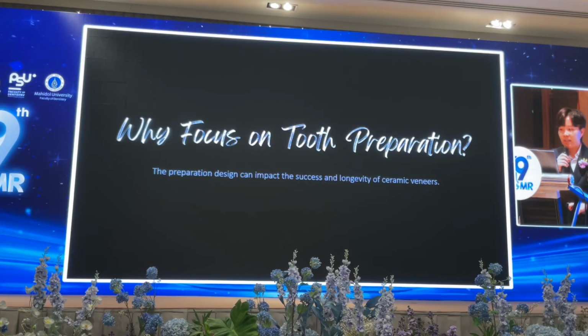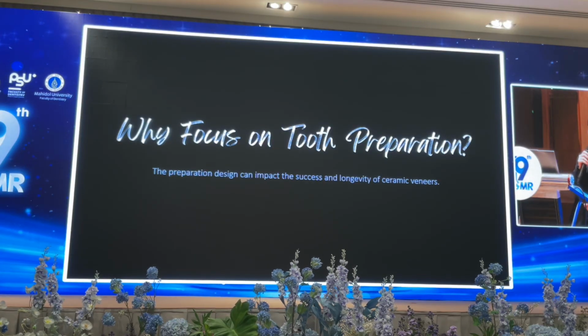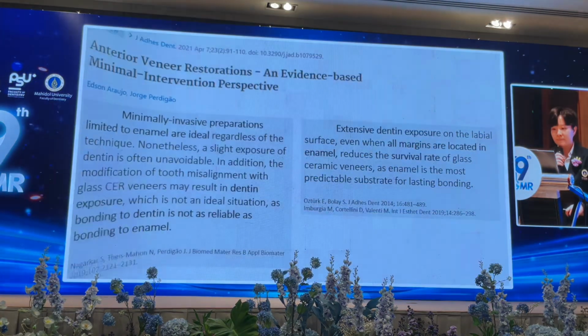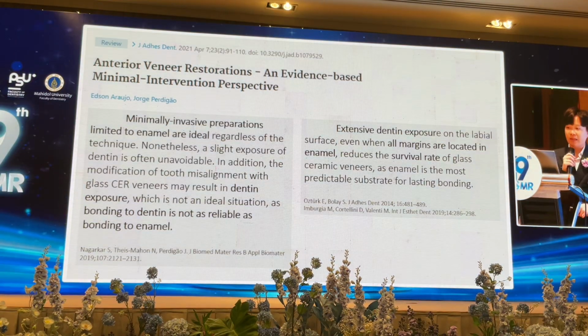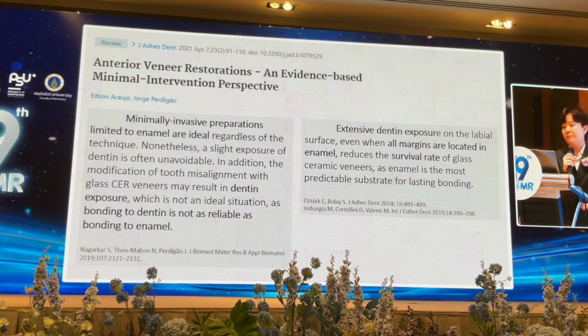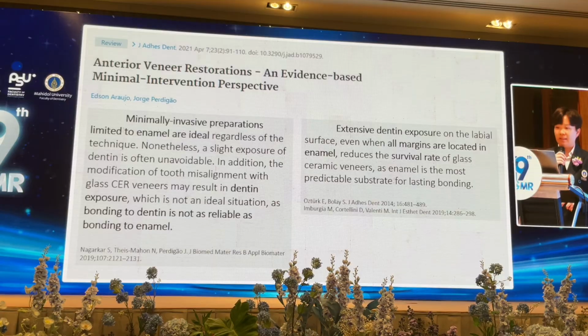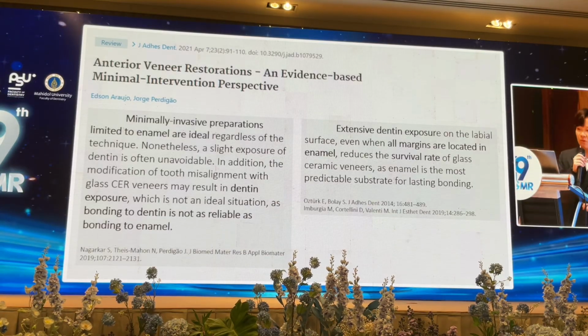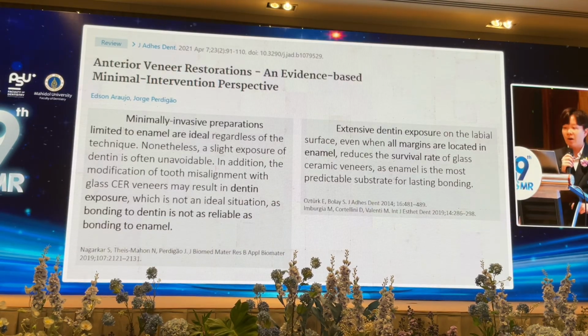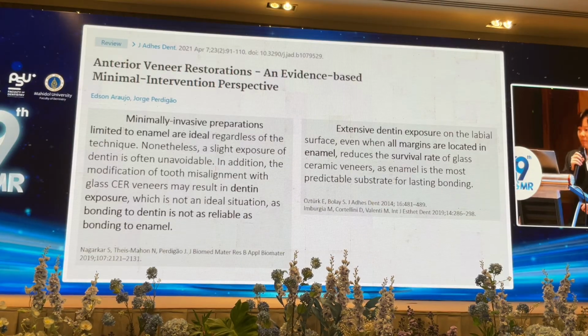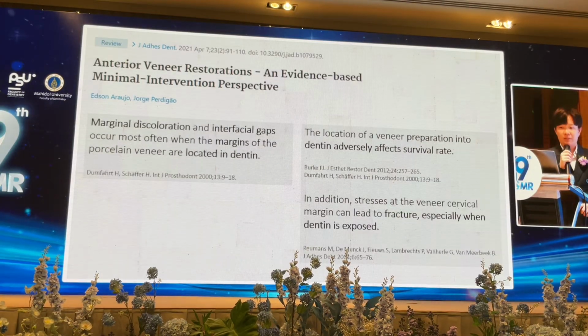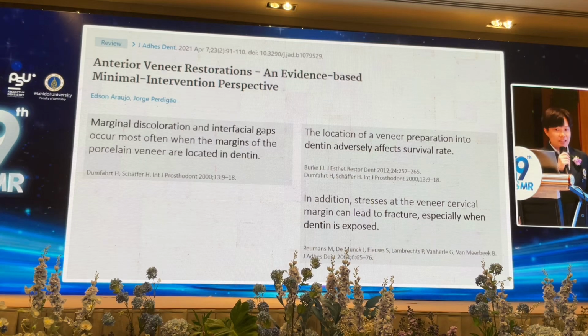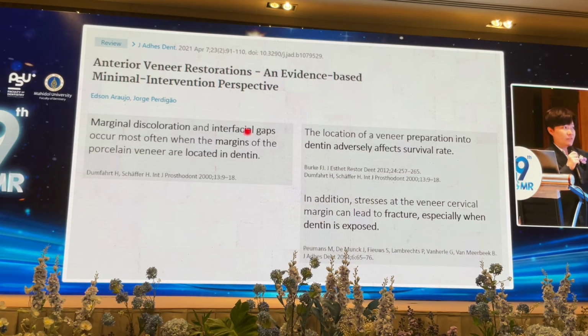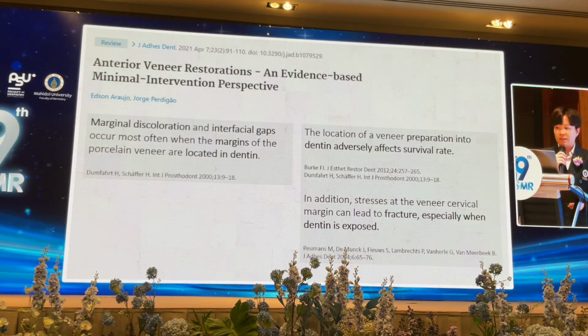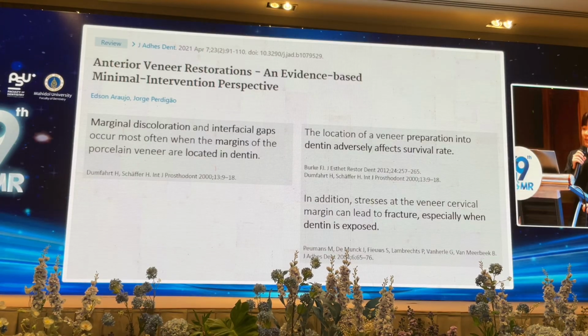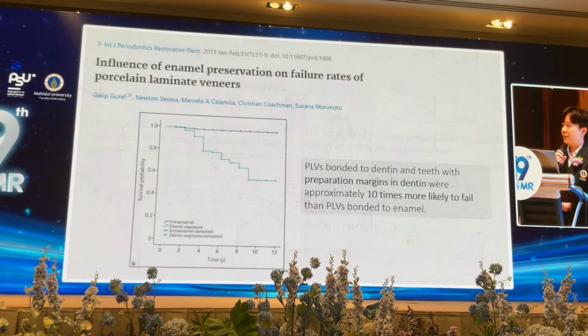The preparation design can impact the success and longevity of ceramic veneers, and many studies agree on that point. Minimally invasive preparation should stay within the enamel. Exposing dentine can cause several issues. The bond is less reliable than on enamel, which lowers the restoration survival rate. And it can also lead to marginal discoloration, interfacial gaps, and of course, fractures. So preserving enamel is absolutely critical for long-term success.